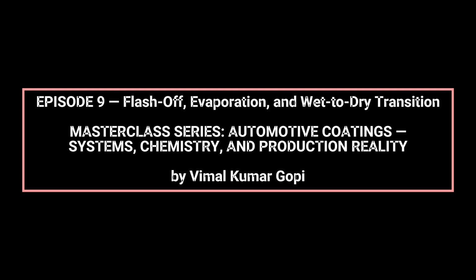In OEM production, variability in booth airflow, line speed, body temperature, and environmental conditions shifts flash-off behavior daily. A formulation that performs well under laboratory-controlled flash times may fail when exposed to real production variability. For this reason, OEMs define acceptance limits and process windows, not ideal conditions, and evaluate coatings for robustness rather than peak performance. Our R&D teams therefore design solvent packages to tolerate shorter and longer flash-off times, ensuring acceptable appearance, adhesion, and durability across realistic plant conditions.